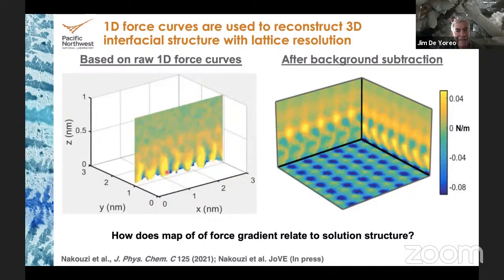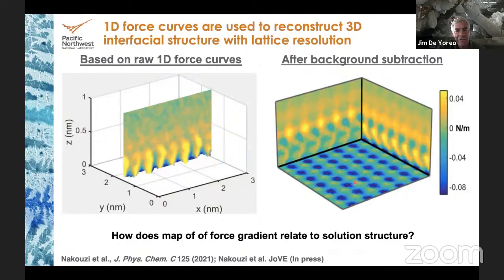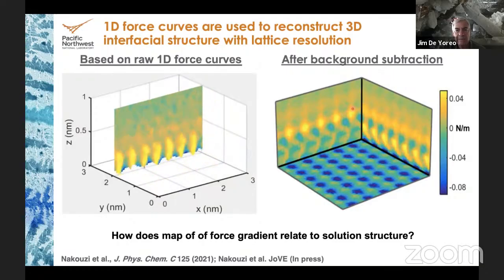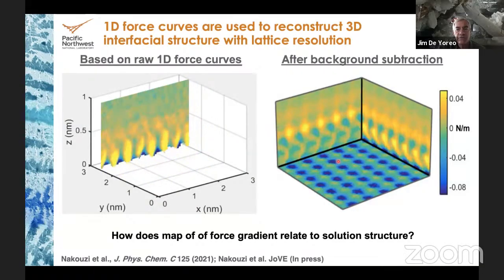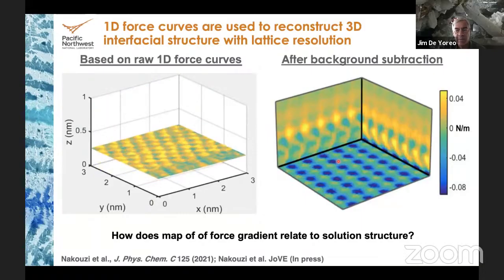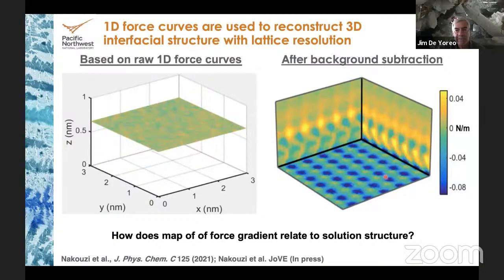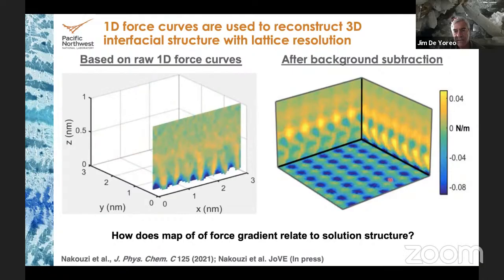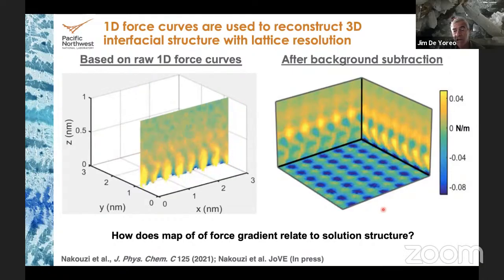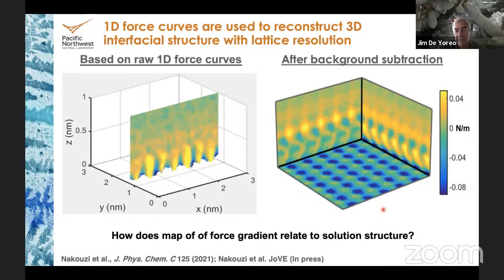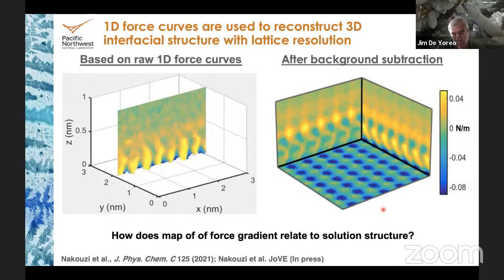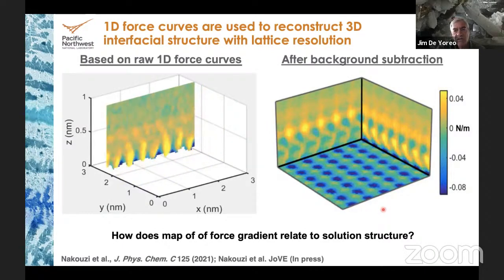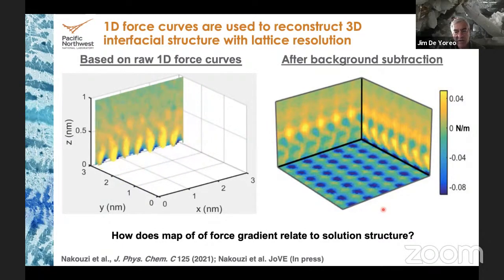If we then subtract out the background, we get this truly amazing detailed map of hydration structure. It's really just mind-boggling that it's possible to map this out. And so this is a lattice resolution map of where the water is. Now, of course, it's not where the water is, it's the force gradient. And the question is, how is that related to solution structure?